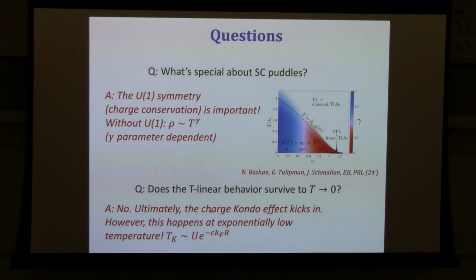It just turns out that in this problem, the effective Kondo temperature where this occurs is exponentially small in this parameter k_F R, basically with the number of electronic channels that are trying to screen this impurity. Okay, so this is something we rediscovered. It turns out this was a phenomenon that was known in the literature. If you have many channels trying to screen the same spin, if you tune them all to be exactly the same coupling strength, they would never be able to screen. They just compete all the way down to zero temperature. If you consider some distribution of coupling constants, then you do screen eventually. One channel wins, but that happens only at exponentially low energy scales in the number of channels.